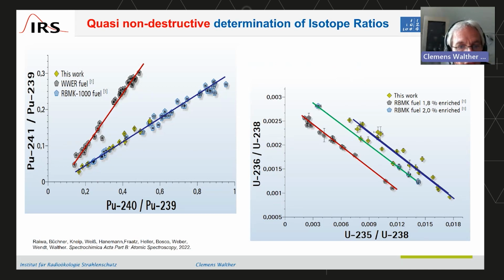So if we throw everything together, we build so-called 4 isotope plots. These 4 isotope plots give you here the ratio of plutonium-240 to 239 on one hand. Just remember, the weapons plutonium was at the very low side and the reactor plutonium here. In the same plot, we also scale the plutonium-241 to 239. The green dots are what we got from that handful of dirt. So we found particles here. And we know from literature, from the database, how that should look for a pressurized water reactor.